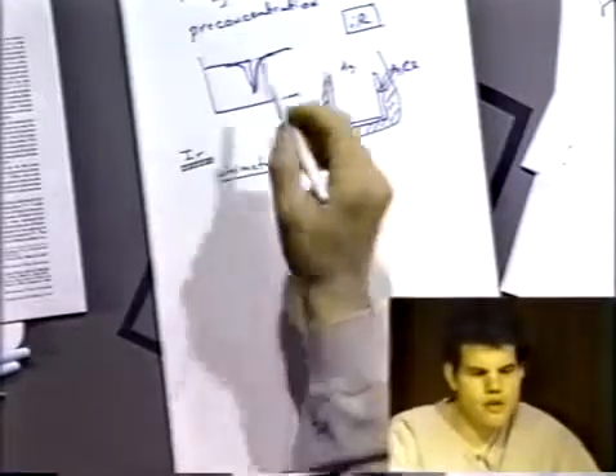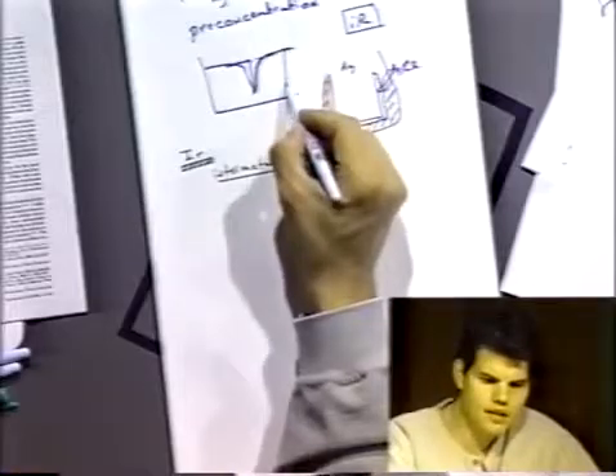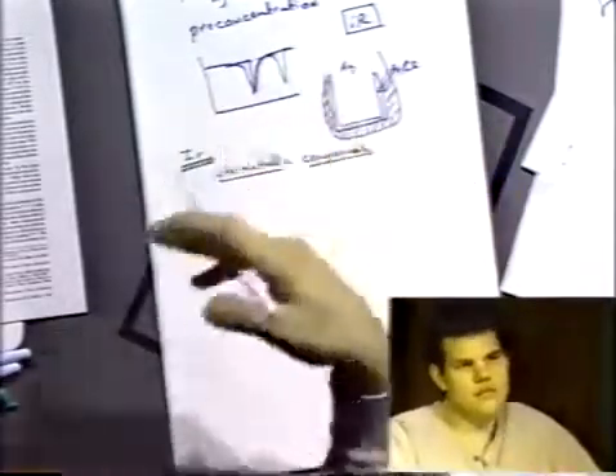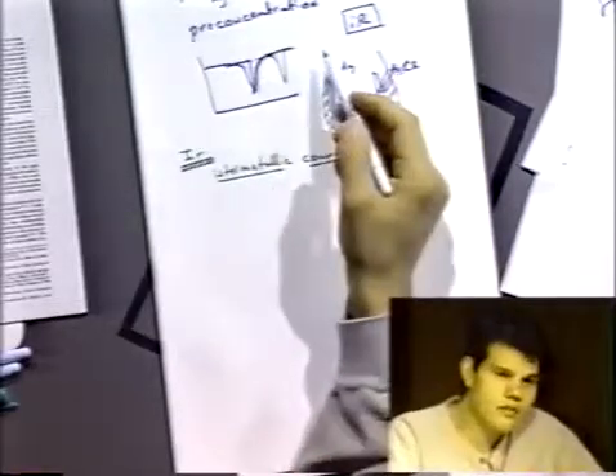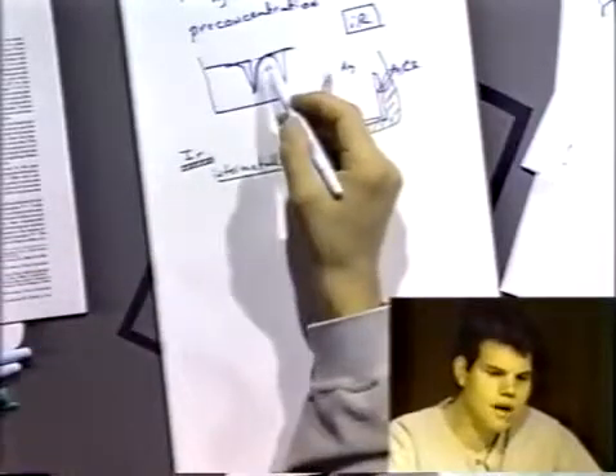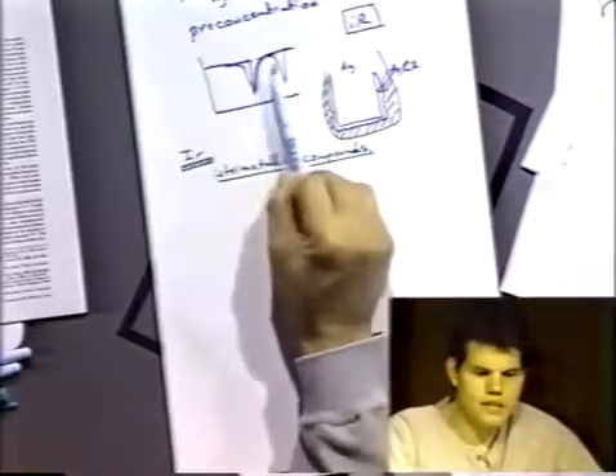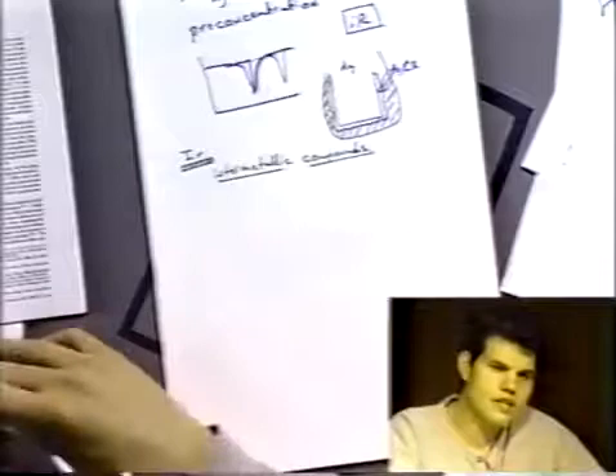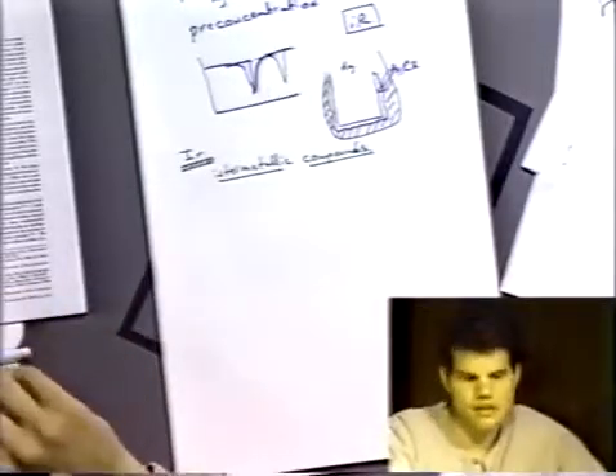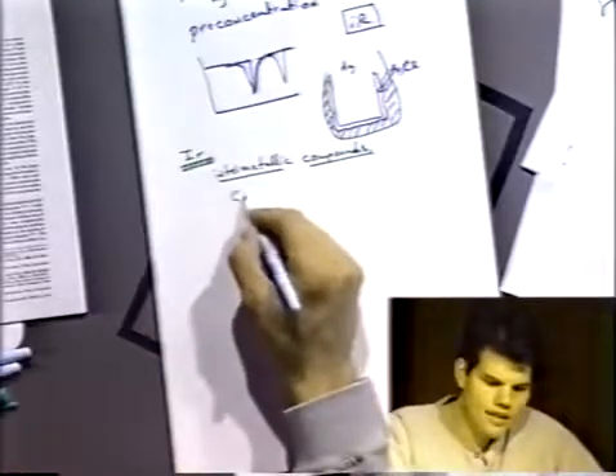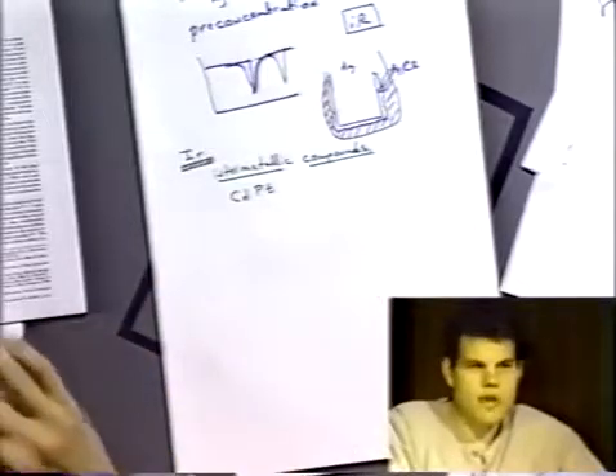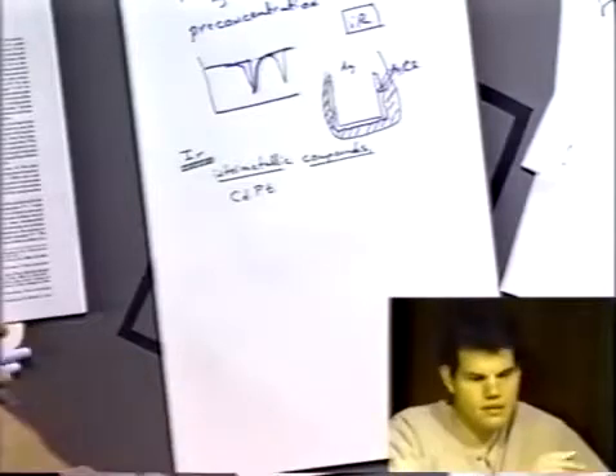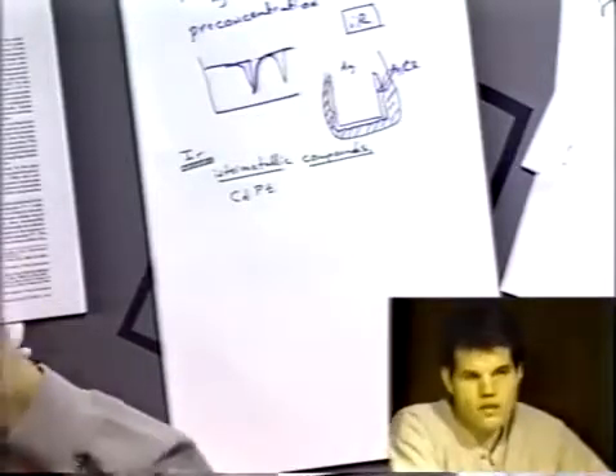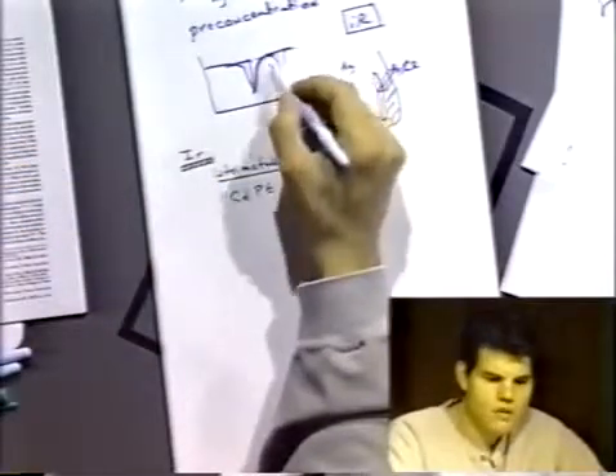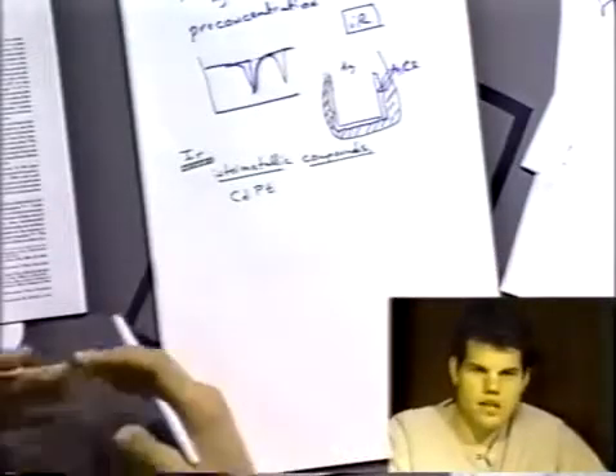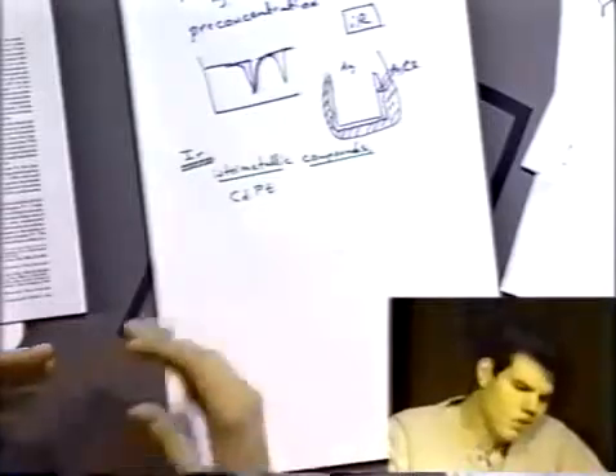The reason is that what you want to do is, when you see these peaks coming off, they're diagnostic. So they'll strip off at different potentials depending on the redox potential of the material that you're getting. And so you want peaks at different potentials because for real samples, you might have cadmium and copper and silver, whatever in there. So you want to see different peaks. The problem is, especially since you're pre-concentrating it, now the mercury has a relatively high concentration of material in the small mercury drop. And what you can find is that things like cadmium and platinum form complexes of the metals in the mercury itself. And because of the energy of that complex formation, you don't get the stripping wave at the peak characteristic of cadmium alone. You get a peak characteristic of the cadmium-platinum complex.